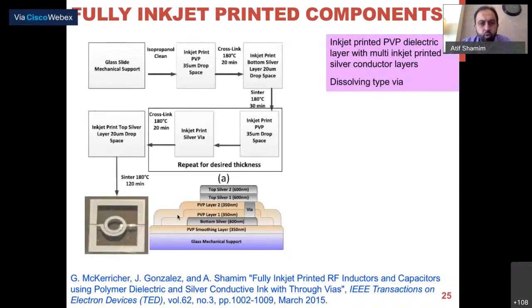This via is called a dissolving type of via. It's because these layers are thin, so we do not need any laser or anything like the previous slide I showed you. Here, what we do is when we print the dielectric layer, we actually don't heat it. When it is wet, we pass the metallic ink from where we want the via. So the metallic ink just seeps through, reaches the other side, and then we heat it, and then it solidifies and no more ink seeps through, and then you could print metal on it. So that's why you can print multiple layers and you can connect them through vias. And we did a lot of inductors and capacitors and antennas in this process. This is showing you the vias and the inductors.